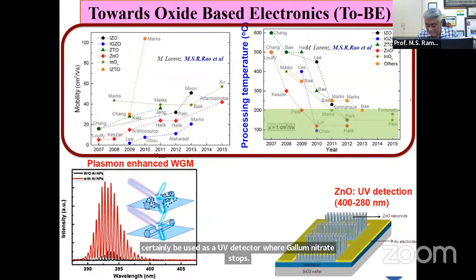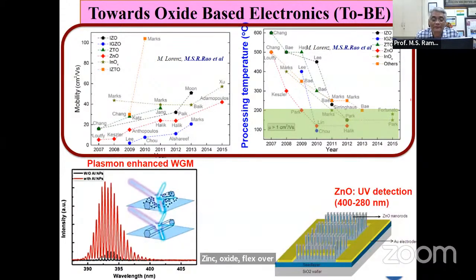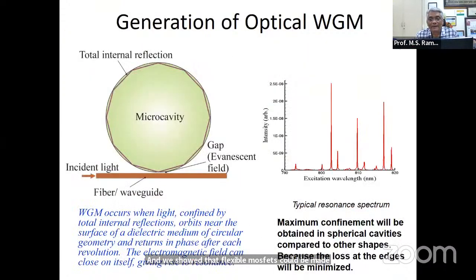Zinc oxide is a very good material for plasmon enhanced whispering gallery modes, and tin oxide also. It's a material that could be easily deposited, using even spin coating techniques, and we showed that flexible MOSFETs could be made with tin oxide.